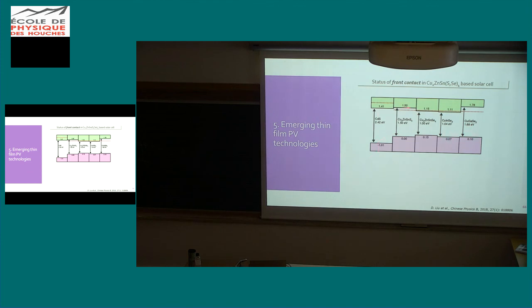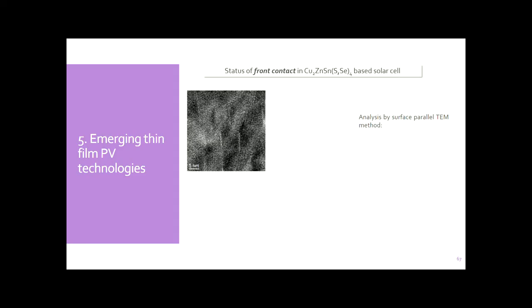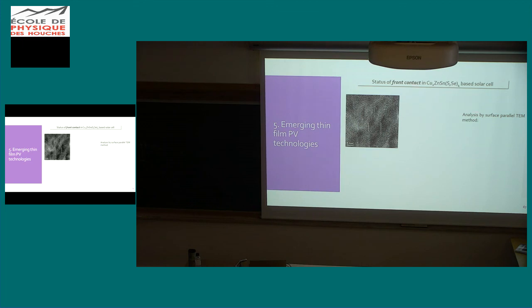In terms of band alignment, with the selenide compound, the band alignment is perfect. With the sulfide, you have a small cliff, but it's really small, so it cannot explain the large VOC deficit of this material. So cadmium sulfide is probably not the best for the sulfur compound, but for the moment it's not the big issue. What we observe studying the front interface, with a special TEM analysis, is that we sputter all the material away from the substrate and observe the surface.